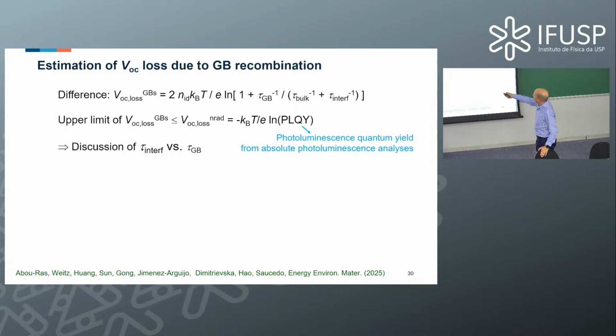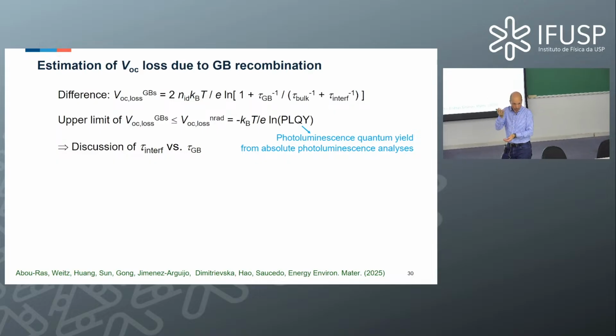And then what we can do is we actually can end up with this equation. Yes, and you can see it only contains the lifetimes in this equation. For convenience, I took one term for both interface lifetimes. Okay, so and then what we can do is to use photoluminescence quantum yield measurements. So actually we can determine this quantity by looking at the emitted photons from a material divided by the number of absorbed photons in a material, right? And this is done by photoluminescence measurements, standard technique.